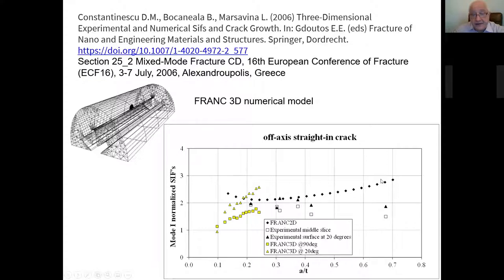This is a Franc 2D solution of normalized stress intensity factor with respect to a over t, so this is simply the ratio between crack length and thickness of the model. Experimental data are shown here with square and triangle. This is the middle slice, square, and the black triangle is 20 degrees from the surface. And here are the numerical values again for the same positions, middle and close to the surface. So we were able at that moment to have numerical values only for these ratios.